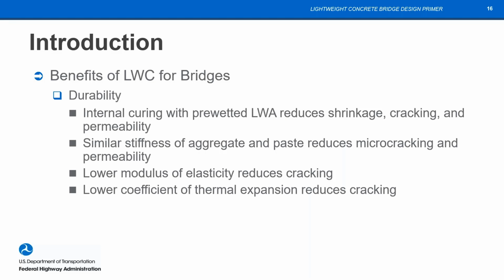What about other benefits? Interestingly enough, lightweight concrete has a durability benefit. It doesn't seem to make sense that using a porous aggregate in concrete would actually improve rather than degrade the durability of concrete, but that's what experience and testing has demonstrated. The pores in the aggregate that make it lighter actually allow the aggregate to absorb water prior to mixing, and then that is made available within the concrete after setting in order to cure the concrete from within, and this is known as internal curing. This feature really provides significant benefits of reduced shrinkage, reduced cracking, and reduced permeability.